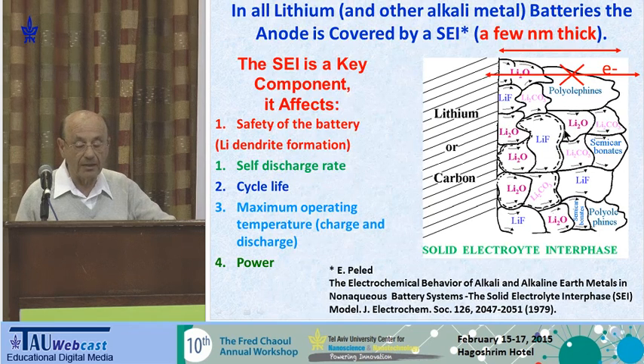There are different particles that precipitate on the surface of lithium or carbon or silicon, and it's lithium fluoride, oxide, carbonate, semicarbonate, some polyolefin. The issue is that we have to stop the electron going from the electrode into the solution. If you don't stop it, you have continuous corrosion and you don't have a battery.